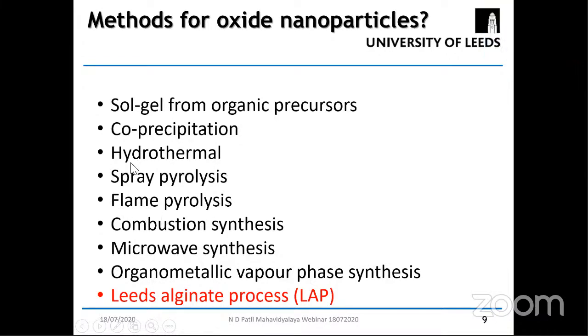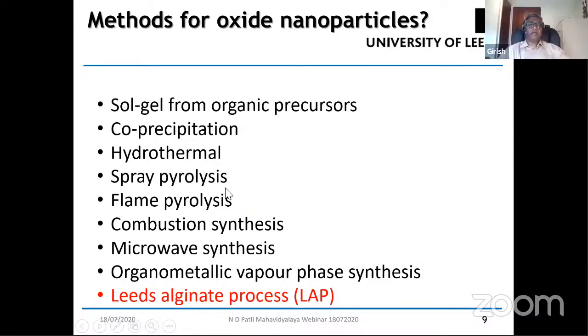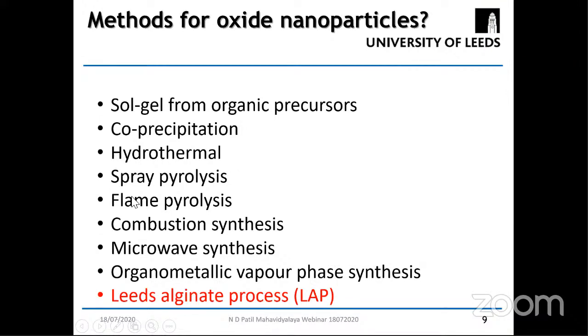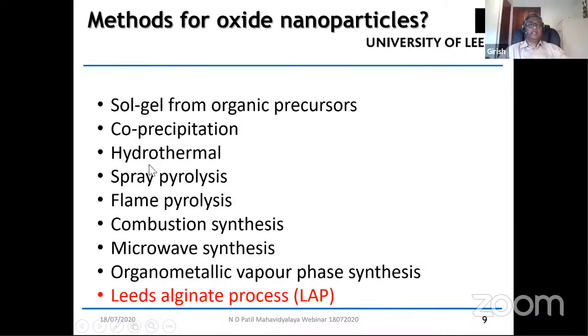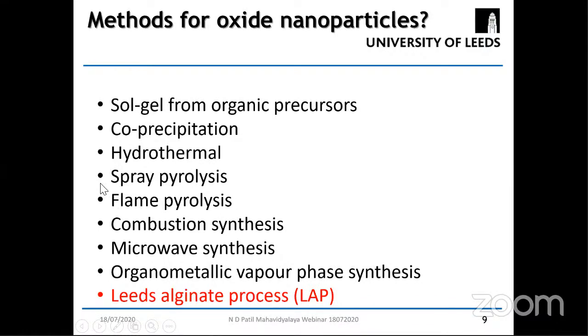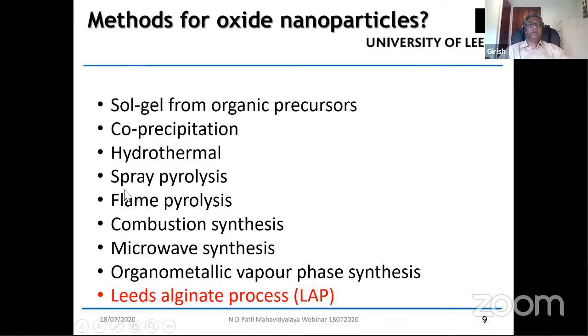Spray pyrolysis and flame pyrolysis are interesting because they can actually be used to produce large scale powders. Well, not nanopowders, but micron size powders. To produce nanopowders using flame pyrolysis or spray pyrolysis is again difficult because of the problems with containment of the particles. There are problems with the containment of the particles because of the nano size of the particles that could potentially be produced from spray or flame pyrolysis if you try to produce them at those scales.